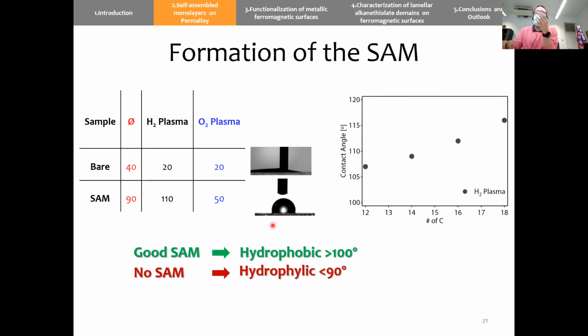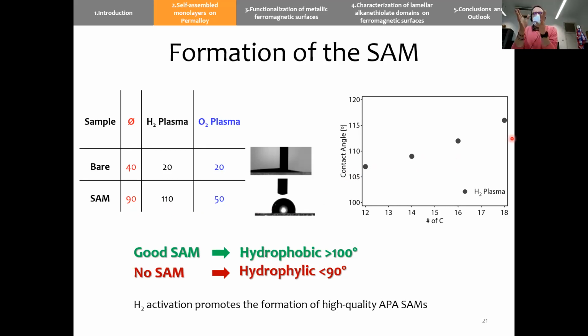Our bare values are: no treatment, oxygen plasma, and hydrogen plasma, which makes it more hydrophilic, at 20 degrees, which was the lowest angle we could measure with our instrument. When we form the SAM, we see that we are well above 100. And also we can see a clear progression as we increase the chain length. So we observe that the hydrogen plasma promotes the formation of a high quality SAM.